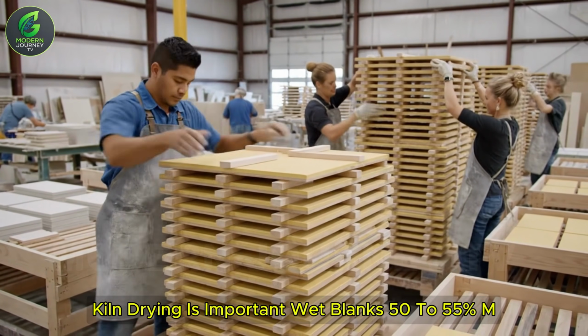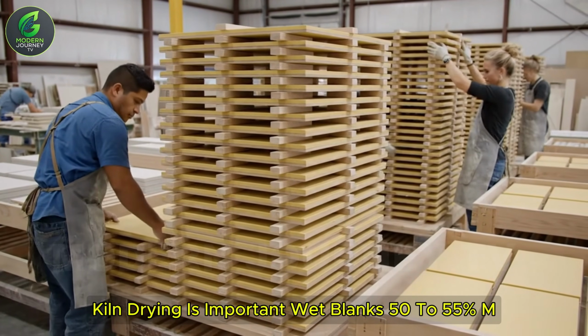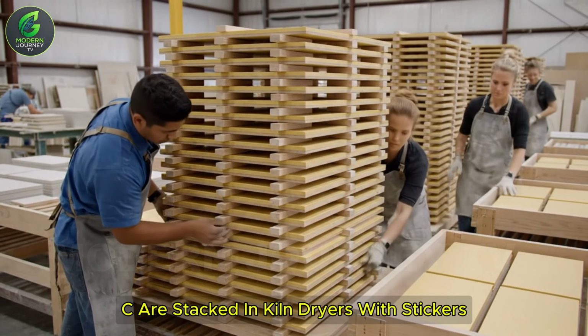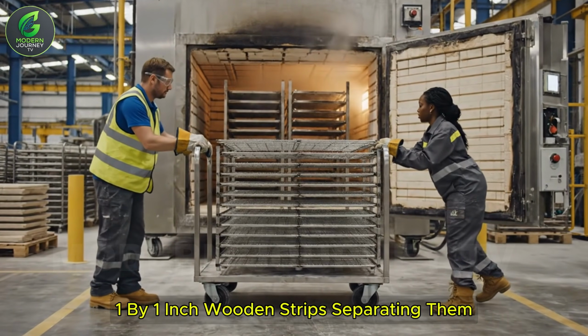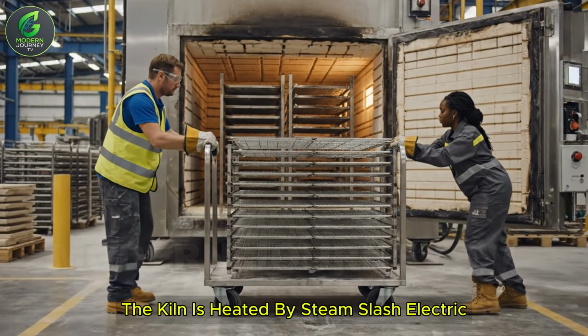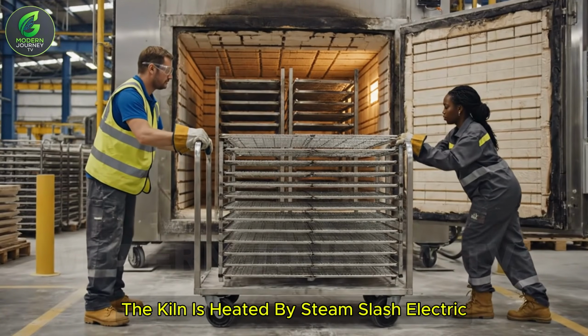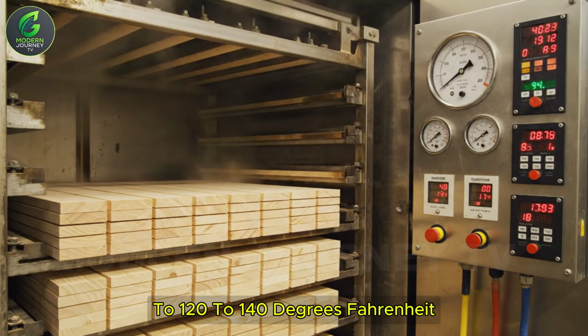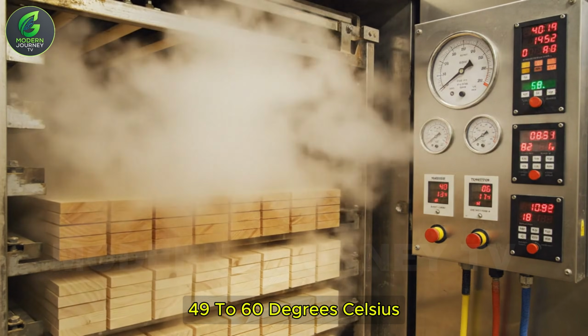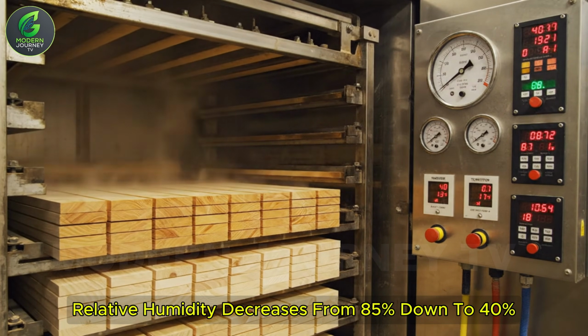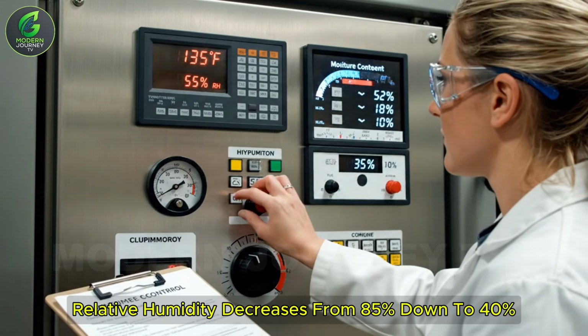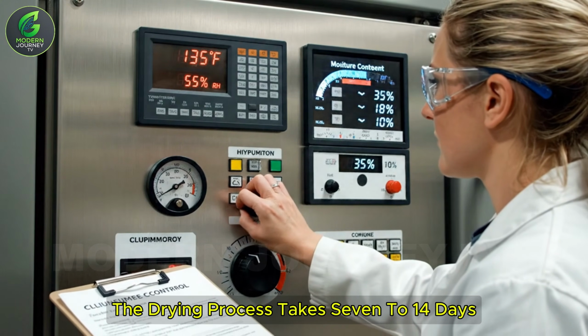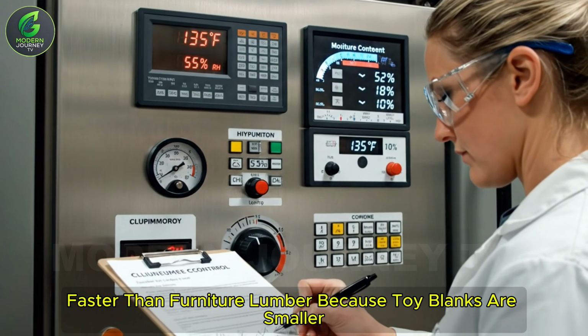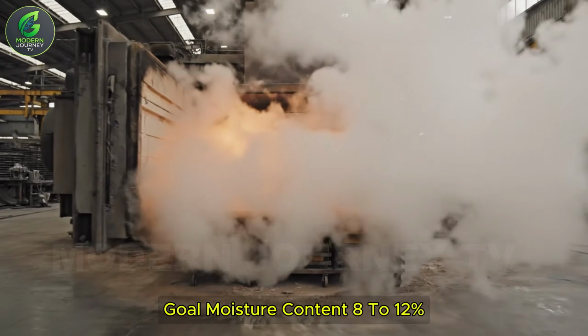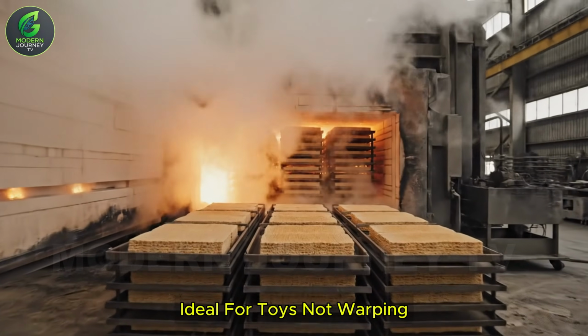Kiln drying is important. Wet blanks, 50 to 55% MC, are stacked in kiln dryers with stickers, 1 by 1 inch wooden strips, separating them. The kiln is heated by steam or electric to 120 to 140 degrees Fahrenheit, 49 to 60 degrees Celsius. Relative humidity decreases from 85% down to 40%. The drying process takes 7 to 14 days, faster than furniture lumber because toy blanks are smaller. Goal: moisture content 8 to 12%, ideal for toys, not warping.